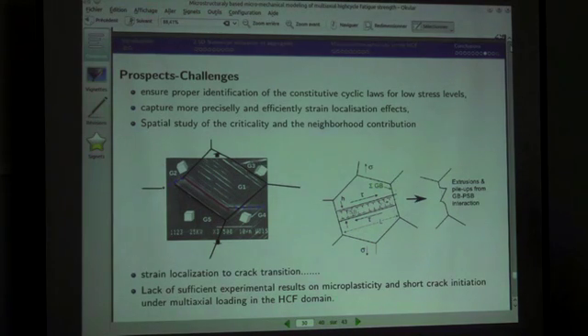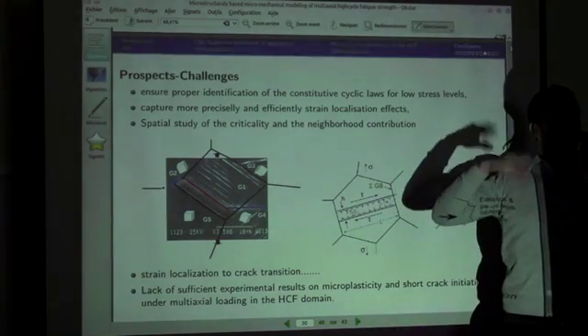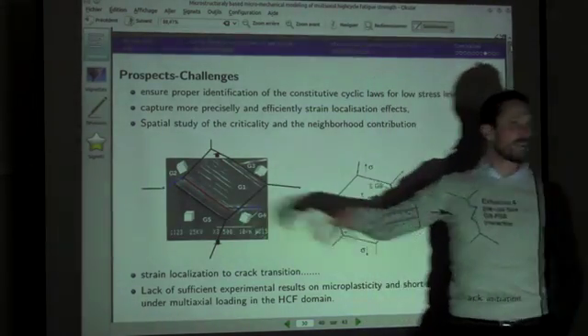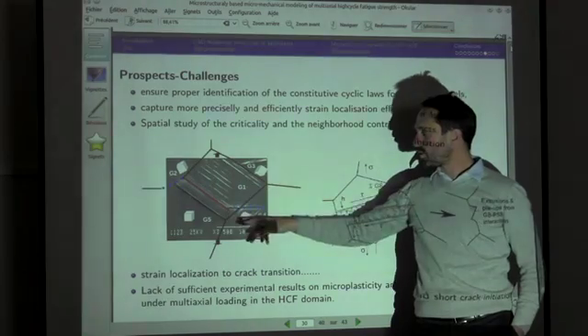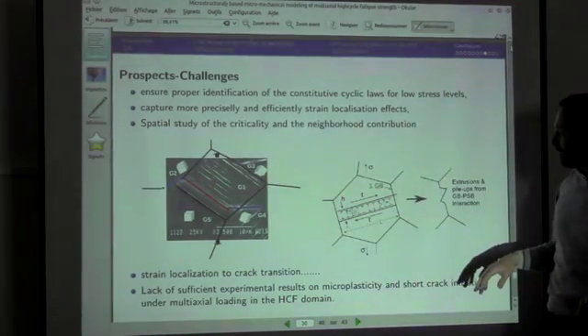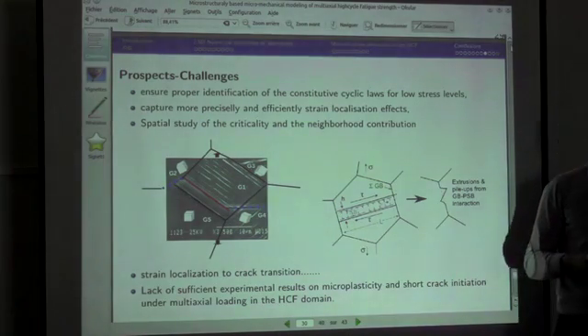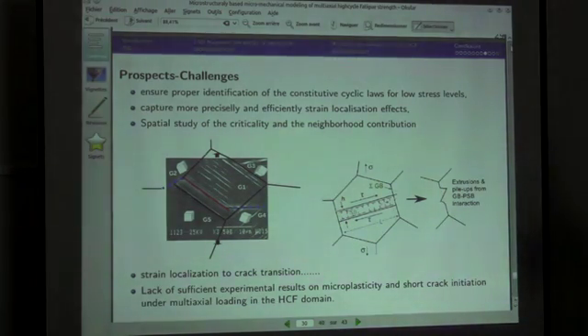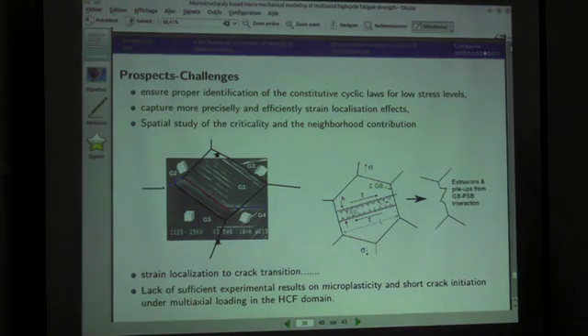Almost the last one is the neighboring effect. We have been computing grains, we have been analyzing critical grains, but as you know, when you look at the material, you don't have a grain which is alone and being critical and saying, okay, the structure has failed. We know that we have some critical grains, but they are surrounded by other grains, in which the response is not only due to the anisotropy and the local plasticity, but also to short crack propagation. And this type of analysis, we are not yet ready to do it. In fact, we are considering each grain as critical individually, but it's very hard to input non-local aspects in the modeling of the damage.